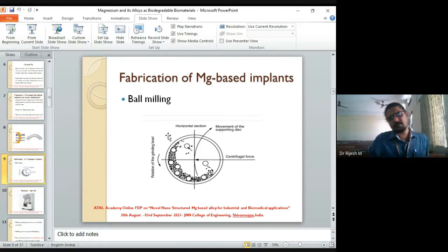In powder metallurgical methods, we can either make a powder out of magnesium or a magnesium alloy. There are many ways in which you can make a magnesium powder. One way is called ball milling. We use hard balls and a lot of magnesium scrap inside, and you start rotating. It's something like a washing machine, it just rotates. Now what happens is a ball will come and hit another ball, and if you have magnesium in between, it gets fragmented. So the size is coming down, and ultimately you will get the size that you actually want. Since we are talking about nano-structured magnesium, you can go for this ball milling to get nano-structured particles also.